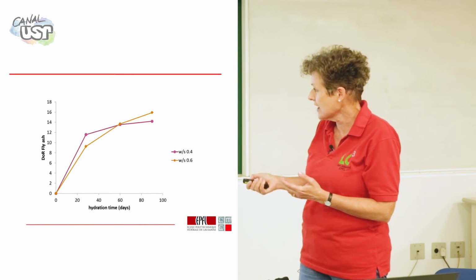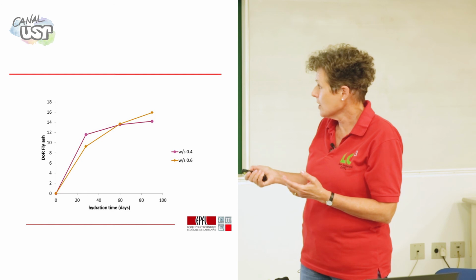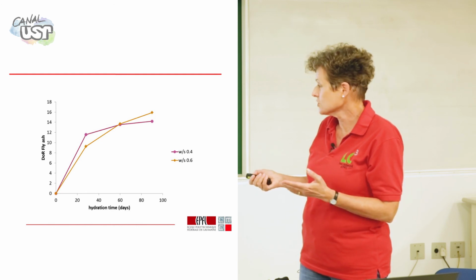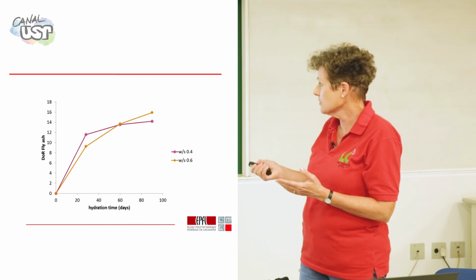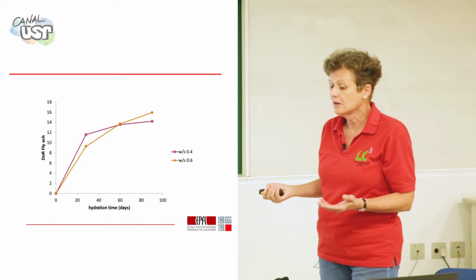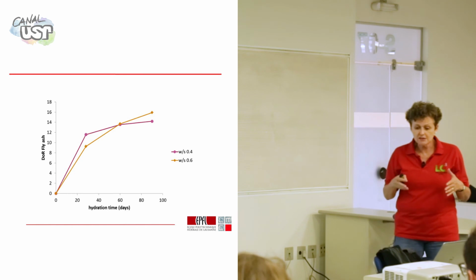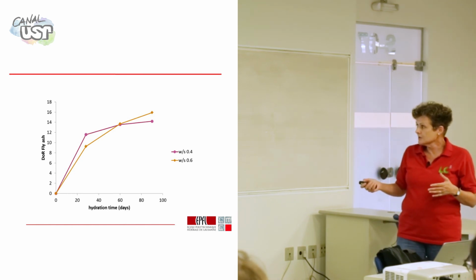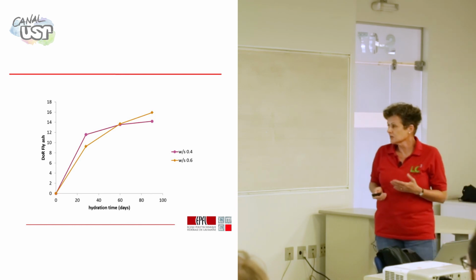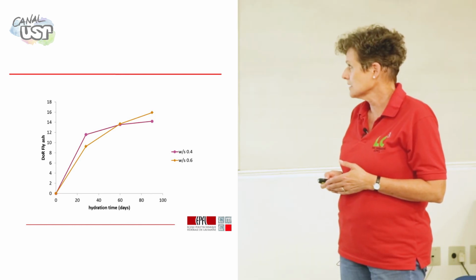So you see the fly ash is reacting quite fast here, but after about 20 days, when we've reached this critical pore size, then the rate of reaction of the fly ash completely slows down. So all these things, the cement paste, the fly ash, etc., are all being limited by what's happening after we reach this critical pore size.